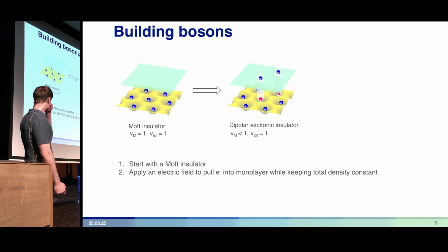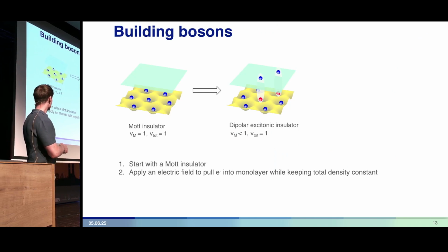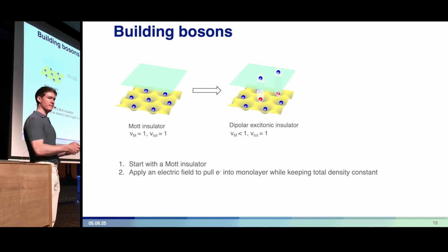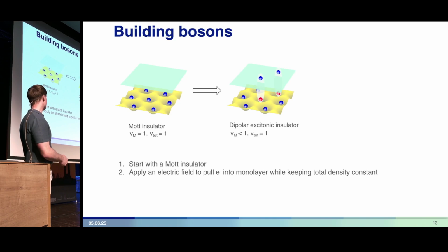So now, as mentioned, we're going to start with this Mott insulator I just showed you, and then apply an electric field, pulling some charges from the Mott insulator in the Moiré up into the monolayer. These leave holes behind in the Mott insulator, and the holes can bind to the electrons to form dipolar excitons. I'll show you that these form an insulating state.